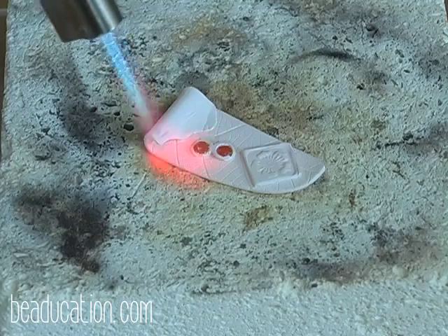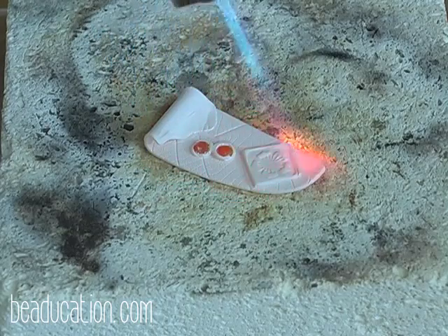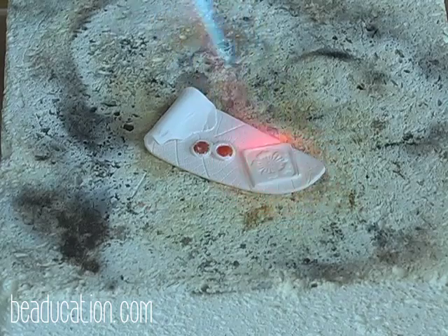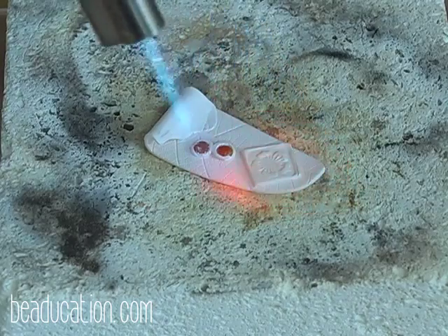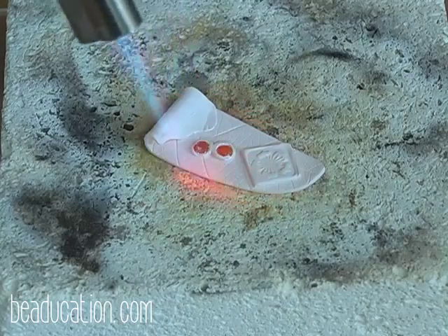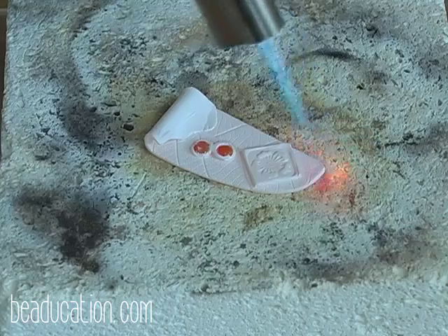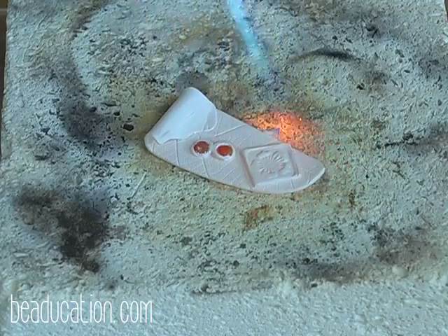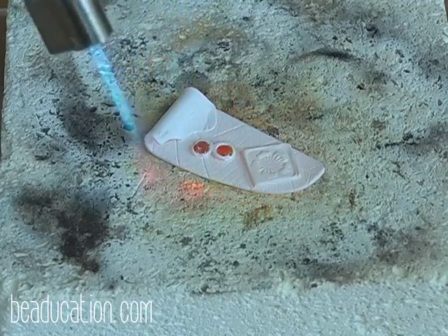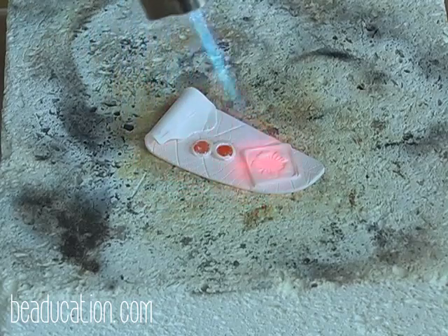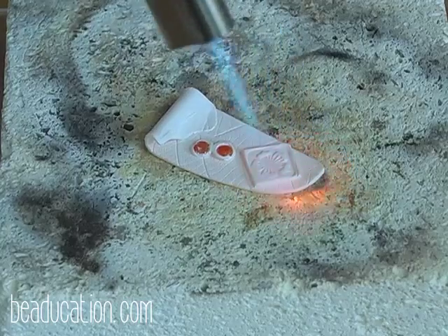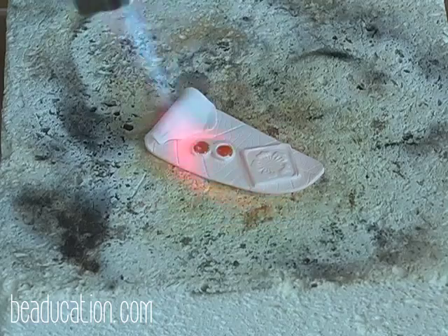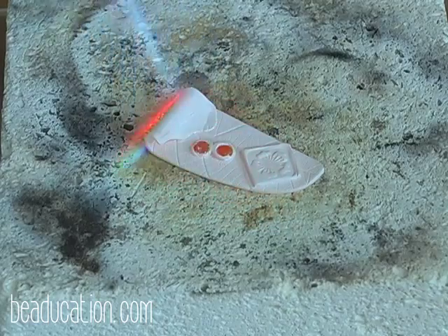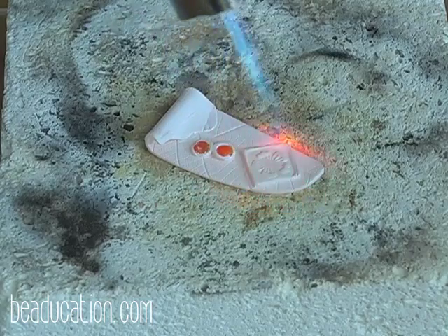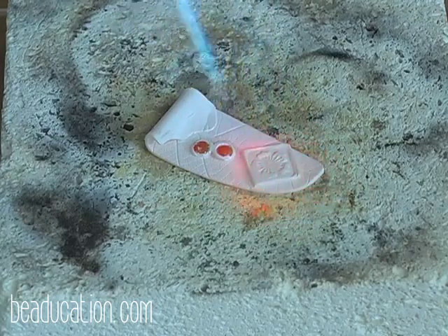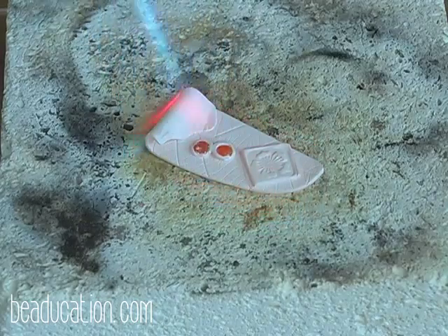You can overfire your piece, and if you're moving your torch too slowly and you let the torch rest in one place, you might start to melt your metal, because now this piece is no longer clay. Once that flame appears, the clay is all burnt out, and this is fine silver now. So we want to keep the torch moving. If you see a flash of silver by your torch, remove your torch quickly, because that means that your piece is starting to melt. But you can see I'm just keeping it even.